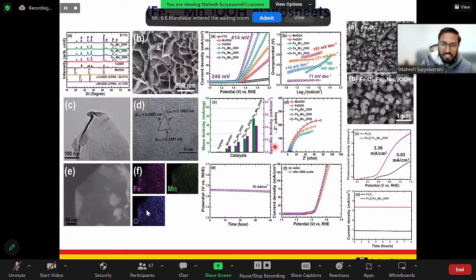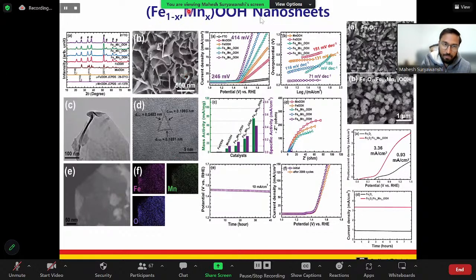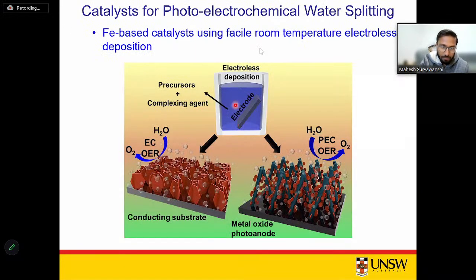So this is one of the catalysts that we have prepared based on the iron manganese oxide nanosheets using the electroless deposition approach, which is nothing but simple. So what you have to do is simply take the precursors and the complexing agent, prepare the aqueous solution of it, and then simply put your electrode into it. And then after 10 minutes of reaction, you will see the catalyst has already been grown on any conducting substrate. So it can be either FTO, nickel chrome, or any other conducting substrate. But simultaneously, it can be also deposited on any semiconductor materials as well, like a metal oxide or chalcogenides.